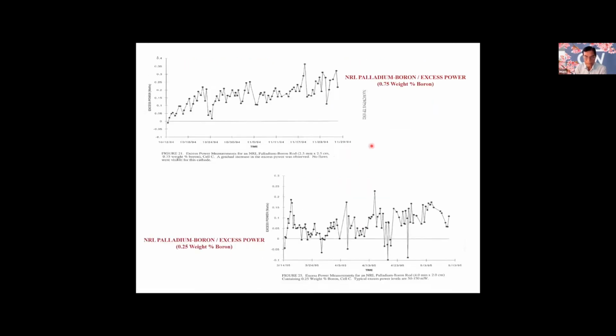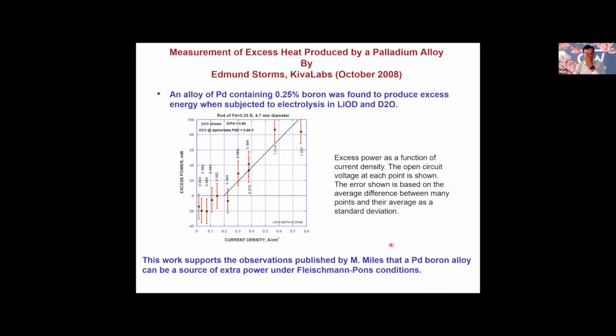And this is for palladium boron, and I'm just giving it for 0.75. Again, this was aimed at 0.75, but we ended up with 0.62 boron content. And you can see the excess heat here. And here is for 0.25 boron. And again, you can see the excess heat there. And we sent some samples to Dr. Storms also, and he also got positive results.